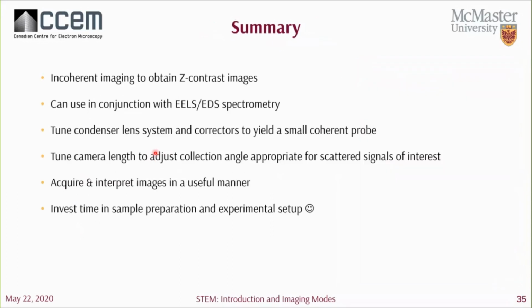All right, so in summary, Z contrast images arise from incoherently scattered electrons, giving us our Z contrast images. We commonly use them in conjunction with EELS or EDS spectroscopy. You can tune the condenser lens system to give you a really small coherent probe. And then you're also going to want to tune the camera length to adjust the collection angle that's appropriate for scattered signals of interest.